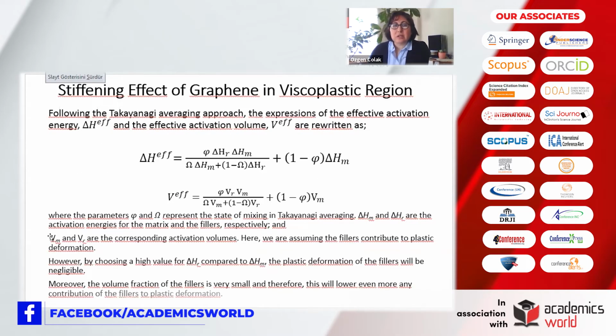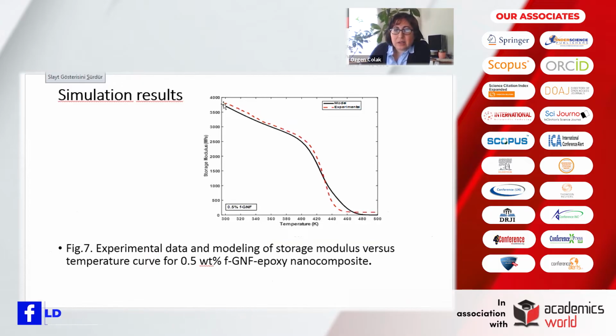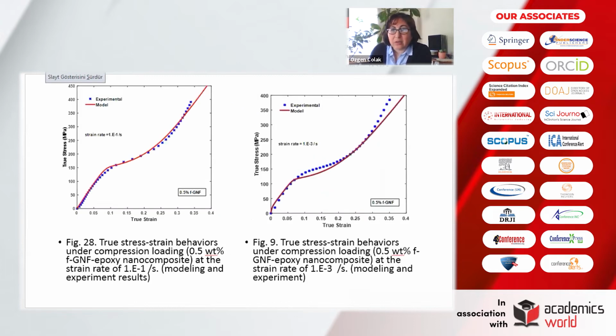If we look at some of the simulation results, this is a storage modulus versus temperature curve. This is basically a result of the DMA, dynamic mechanical analysis. And as you have seen, this dotted line is experiment and the solid line represents the model. Graphene is in the amount of 0.5% as a weight fraction. And as you have seen, the change of storage modulus with temperature has been simulated quite well using some of the parameters that we obtain from DMA. We simulate the next behaviors.